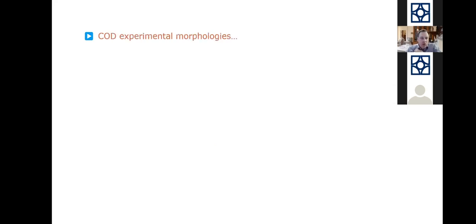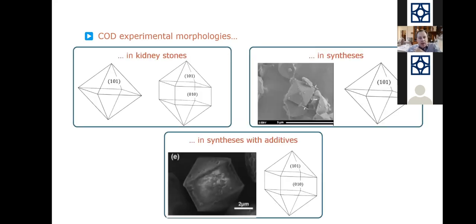Good. Now we can do the same on the calcium oxalate, but the dihydrate. And these are the start structures. So in kidney stones we have this octahedral structure, so a double pyramid, and we also have the same structure but with this part that is inside between the two pyramids. So this is in kidney stones.